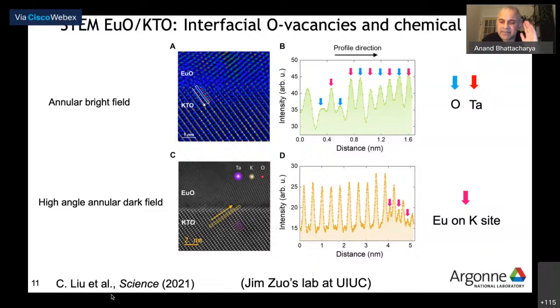Exactly the same thing happens for EuO on the 001 direction, and also very similar things happen when you use LAO, in the sense that lanthanum does get into the top few layers of the KTO. All right, so both of these things, as you all know, oxygen vacancies and cations with higher valence oxidation states, should give rise to electron doping. And that is indeed what we think is going on. We haven't proven it, this is just some circumstantial evidence, but this is what we think is going on.